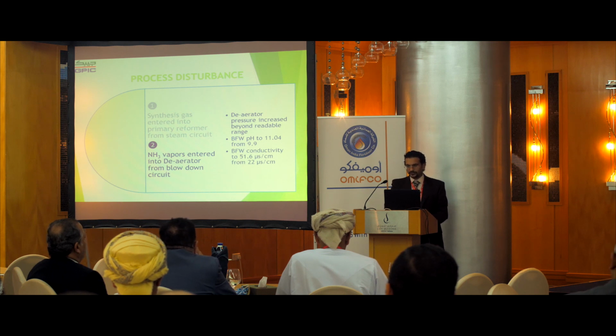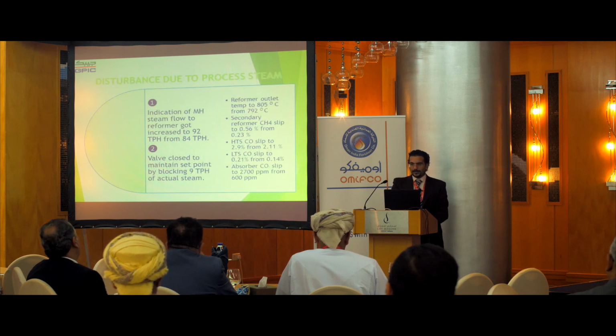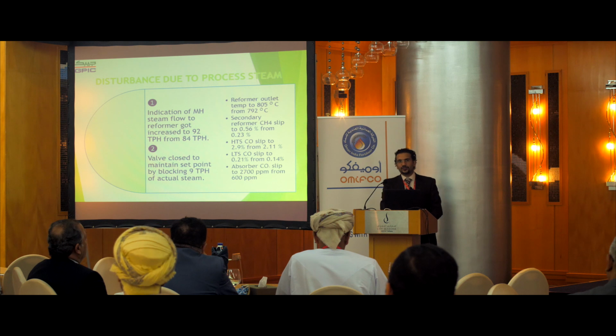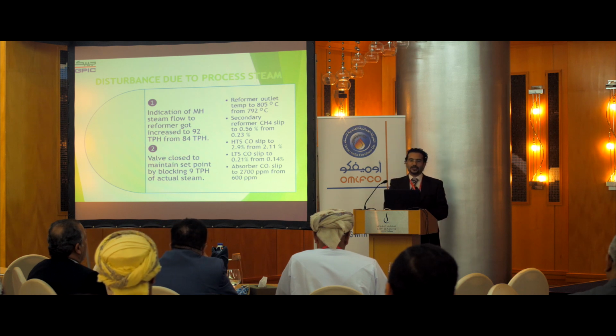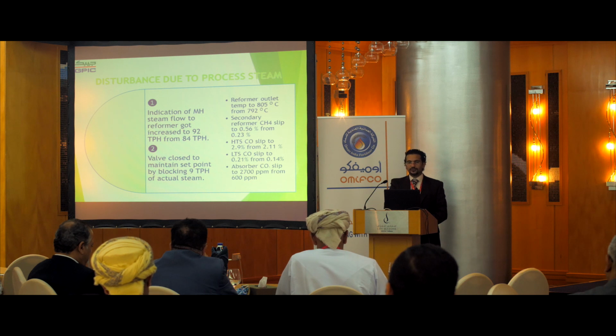It went beyond range. The pH went to 11.04 from 9.9, and conductivity was already high because of our minor or hairline leak, but when it failed, it jumped to 51.6 microsiemens per centimeter. The indication of the medium pressure steam, like I said, increased to 92 tons, so we had to close the valve to maintain our set point.